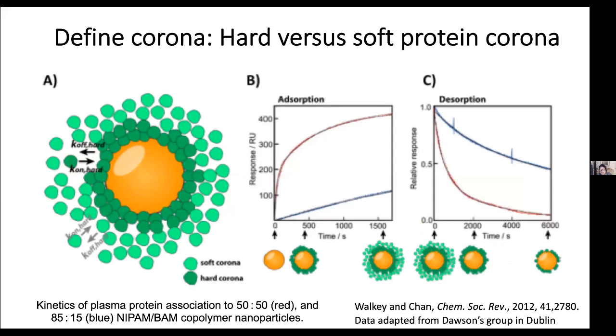The proteins adsorbed onto the surface can be defined as a hard or soft protein corona, terms defined by the Dawson group. Proteins immediately adsorb onto the nanoparticle surface and over time form an equilibrium. Proteins with the strongest binding to the surface are defined as the hard corona. Proteins that are weakly bound above the hard corona are defined as the soft corona, characterized by a very weak Kd value—they come to the surface and slowly desorb. The hard corona contains proteins that are very difficult to desorb from the surface.